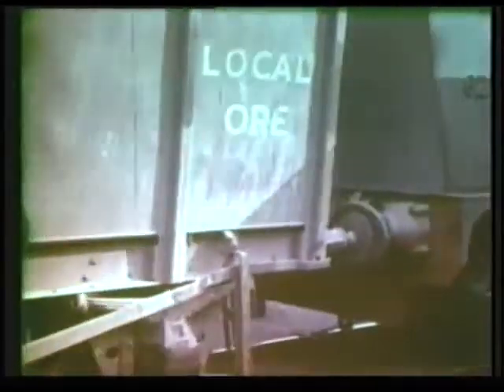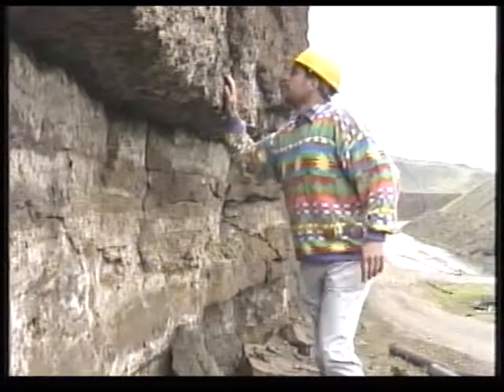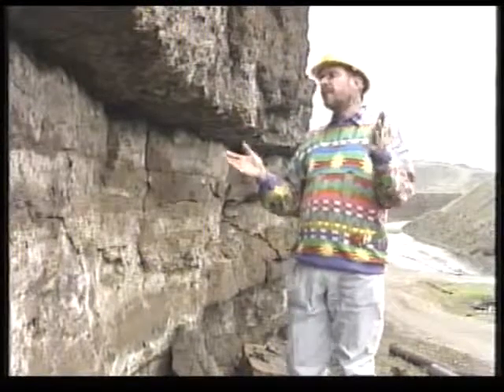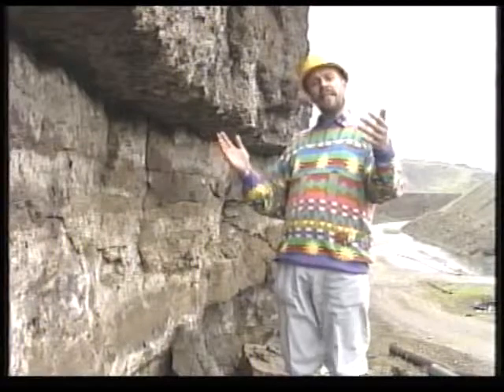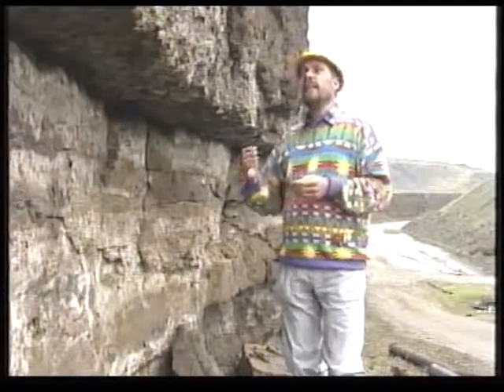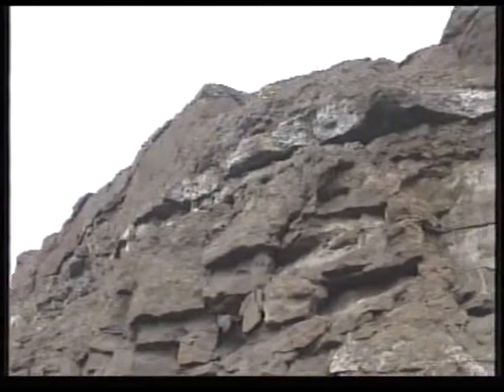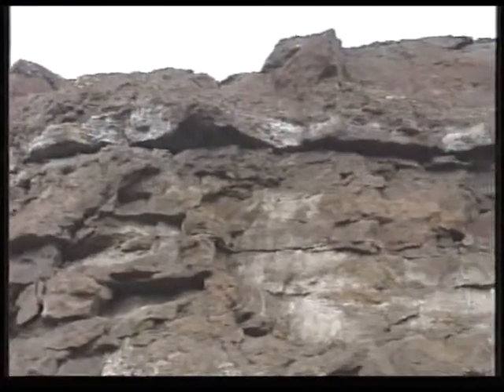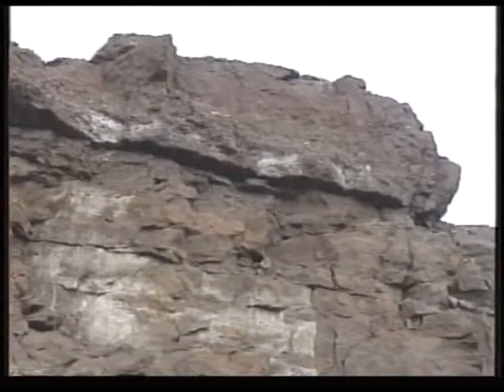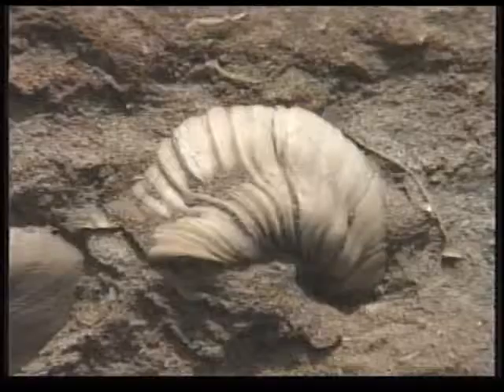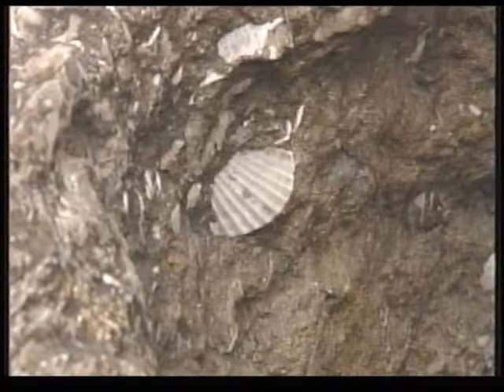A century of steelmaking was celebrated by Scunthorpe in 1990. Sitting on the Frodingham ironstone, another Jurassic iron-rich deposit, the industry developed here because of the proximity of local ore. The worked area of this ore body is about 15 kilometres long and about 10 kilometres wide, and the ironstone itself is about 10 metres thick. And we can tell by these layers and the features within the layers that these rocks were deposited in shallow water. And we know it was the sea because it's teeming with marine fossils.